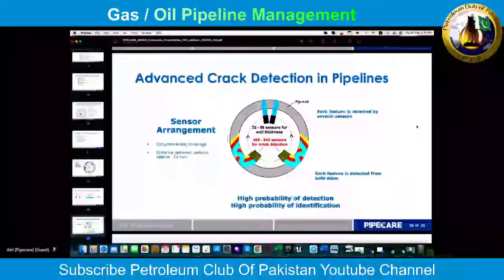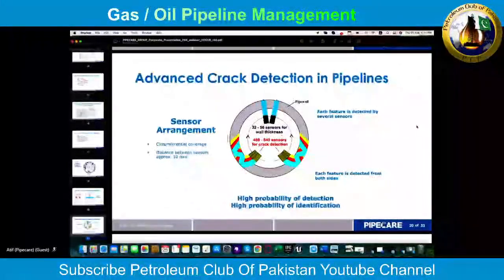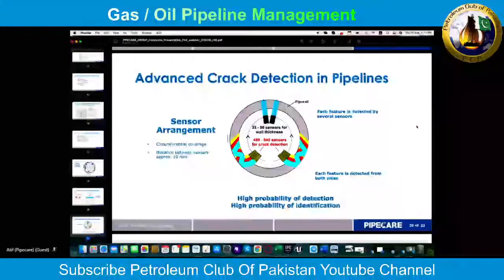What is important is that cracks need to be detected from both sides. This is why we have sensors mounted in 2 directions, so that cracks are seen from both sides. And we also have wall thickness measurement sensors on a crack detection tool, but not in an amount that we could do a full metal loss assessment of the results of the wall thickness measurement sensors. These are important to help the data analyst in detecting the size of a crack, meaning the length and the depth of a crack.